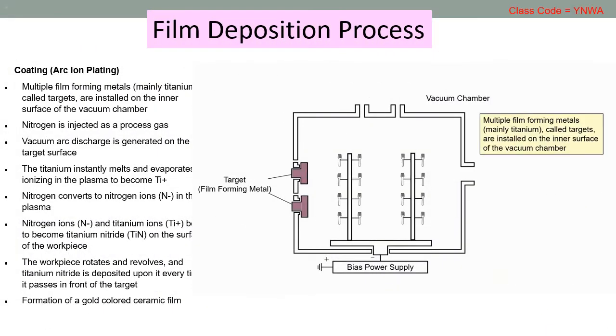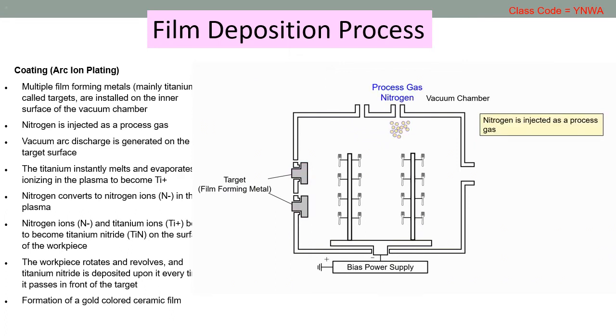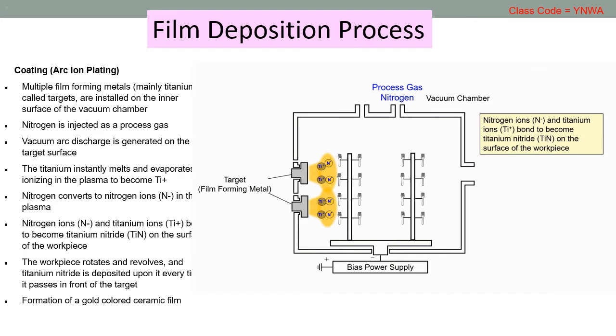Multiple film-forming metals, mainly titanium, called targets, are installed on the inner surface of the vacuum chamber. Nitrogen is injected as a process gas. Vacuum arc discharge is generated on the target surface. The titanium instantly melts and evaporates, ionizing in the plasma to become titanium ions. Nitrogen converts to nitrogen ions in the plasma. Nitrogen ions and titanium ions bond to become titanium nitride on the surface of the workpiece.